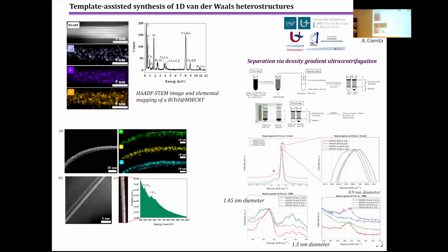One issue in the formation of these systems is that it's very difficult to separate filled nanotubes from empty nanotubes, which is a drawback in terms of the application of the material. So he also developed a separation approach via density gradient ultracentrifugation. In this case, he used solutions with different densities to separate the material by ultracentrifugation. The sample was characterized by Raman, and he observed that after the treatment, he was able to separate the bundles, which are located at the bottom of the tube, from the gray area, C, which is the area with the filled carbon nanotubes, and from the empty ones, which deposit on top of the system.